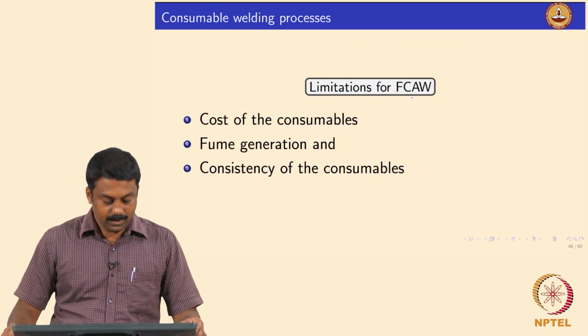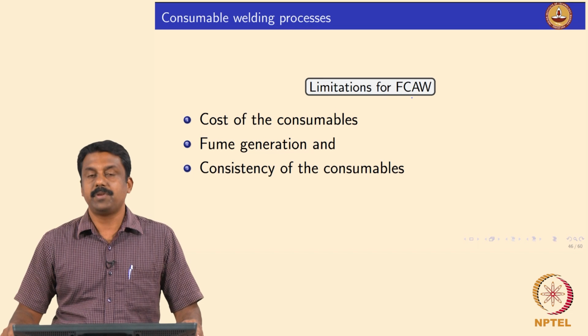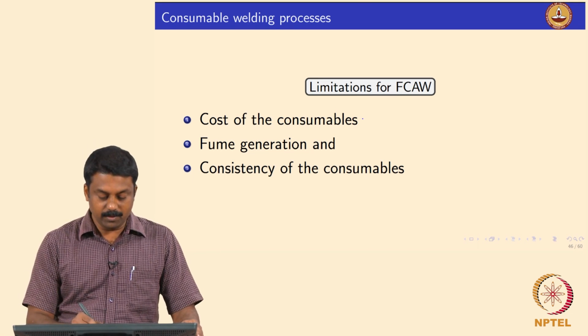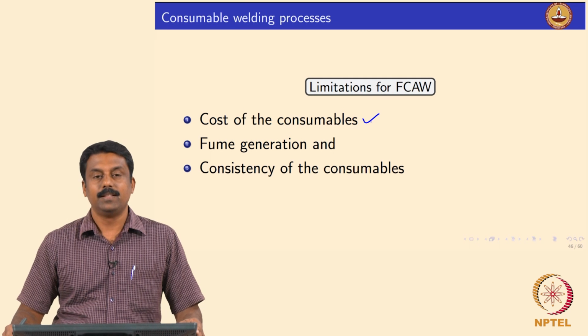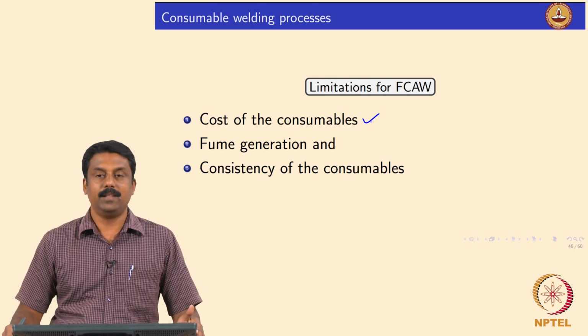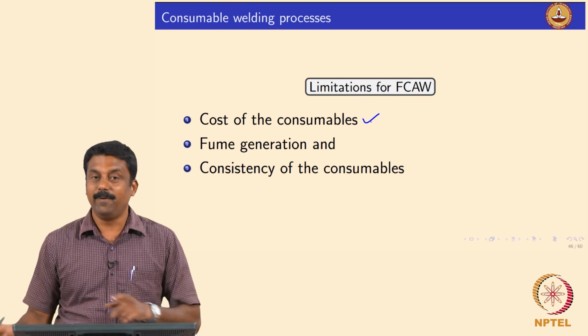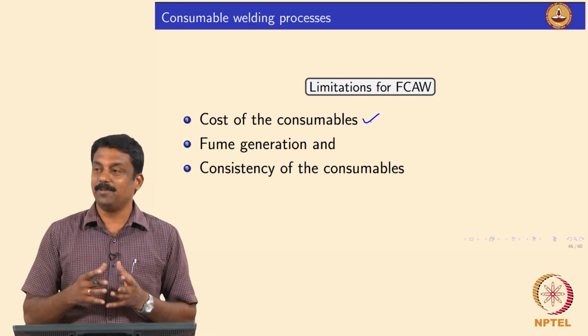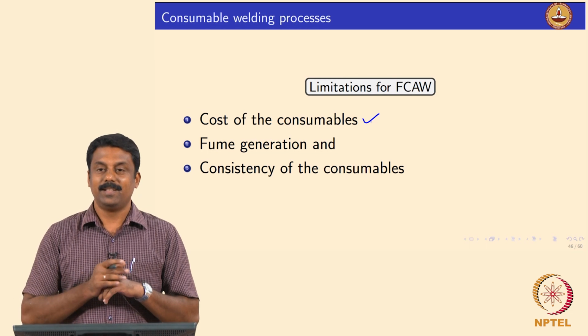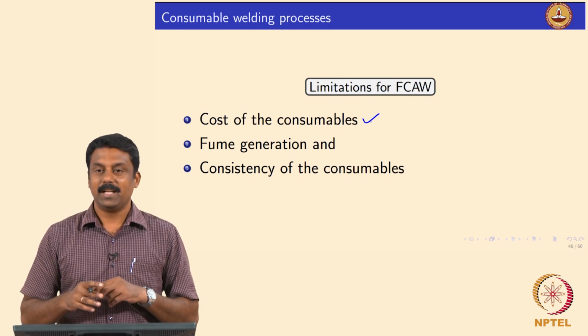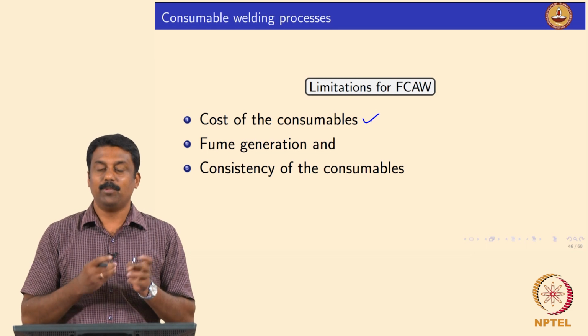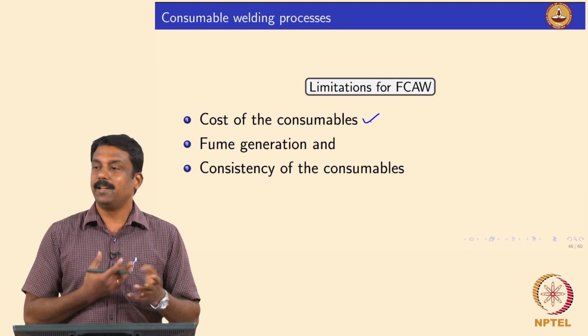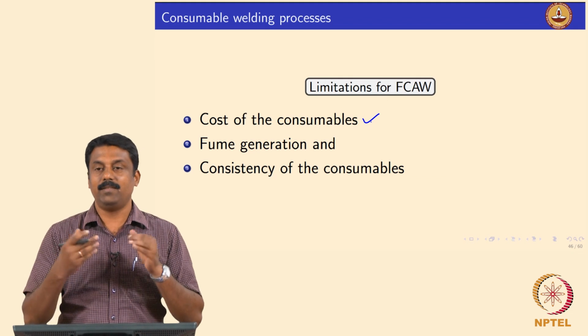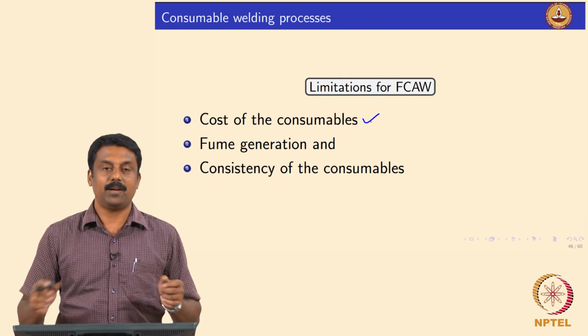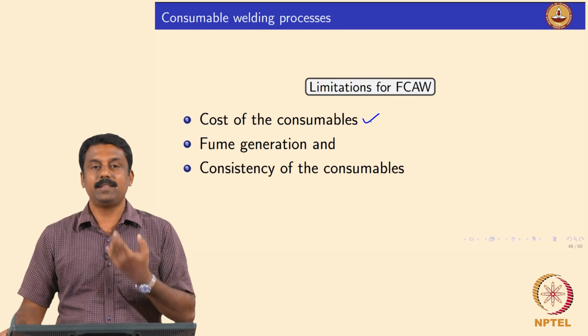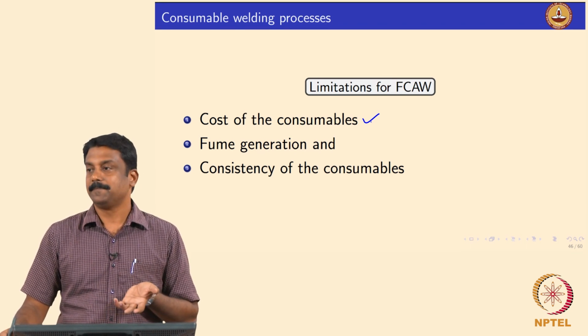Okay. So what are the limitations of FCW? The cost of the consumables. As I said in last class, the consumables are much more expensive than the wire. Although if you look at the actual investment you put up in a factory to make these electrodes, it is reasonably small, but the flux compositions, the work you do to achieve the composition and then generate the electrodes with the flux coating or the flux cored arc weld electrodes, it makes the consumable expensive compared to GMAW,